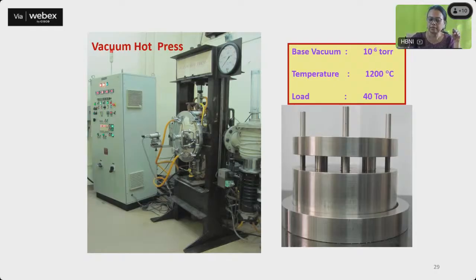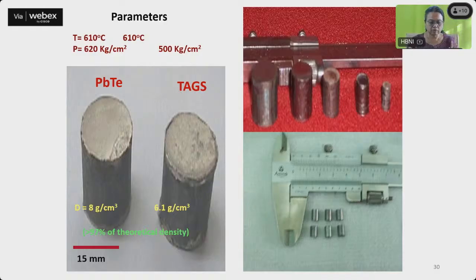we are putting the lid, and now we are vacuum hot pressing. What we do in vacuum hot pressing: the base vacuum is 10 to the power minus 6 torr. Temperature we are going to 1200 degrees, above the melting point, the formation point of our material. And then we are also putting a load of 40 ton, so that our silver legs and all are forming a junction. And this is how it looks.